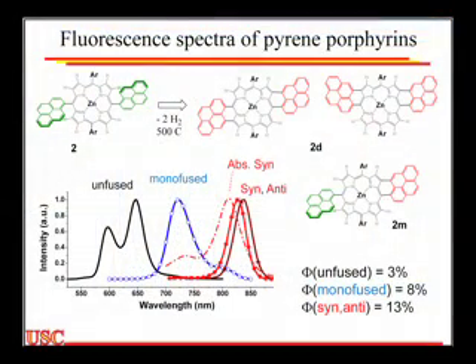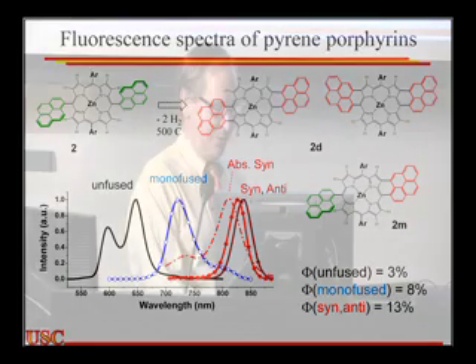So what I really want to do is fuse this one. That is the monoporphyrin. So we throw it in iron trichloride, no reaction. We tried scandium triflate, we tried DDQ, we tried every set of conditions we could find, no reaction. So we got frustrated and just heated it up, and fortunately it works. If we just heat it to 500 degrees, it goes just fine. Quantitative yield of the fused compound.